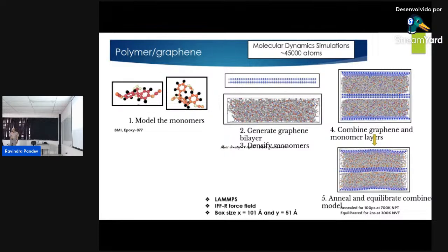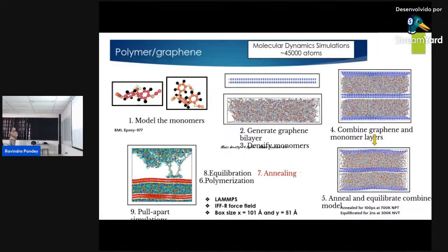So we have gone up to 700K here in different sort of ensembles, and then we equilibrated NVT about 300K. Once you have it, then you do the so-called polymerization step. And then the experiment. So you have this polymerized structure on the NVT model, and now you start pulling it out. Pull out experiment. And this again you can see is a very easy step, but it took about a year to complete this step. So they are very, very expensive calculations.